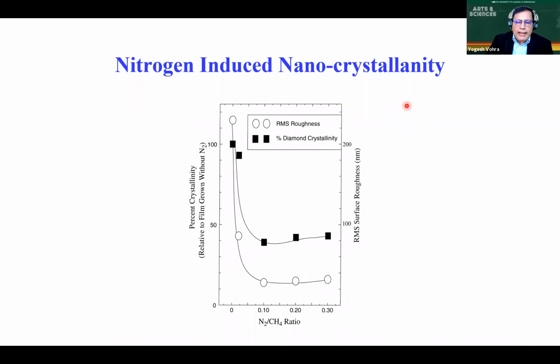And so the practical impact, on the right side here, is a scale of the surface roughness. And you see as we add nitrogen, the film becomes a lot smoother, which is desirable for application. And also on the left side, we do have to sacrifice some amount of crystalline diamond phase, and it becomes a little lower because we do have a more composite looking diamond film, where you have these very small grains of diamond embedded in an amorphous carbon matrix.